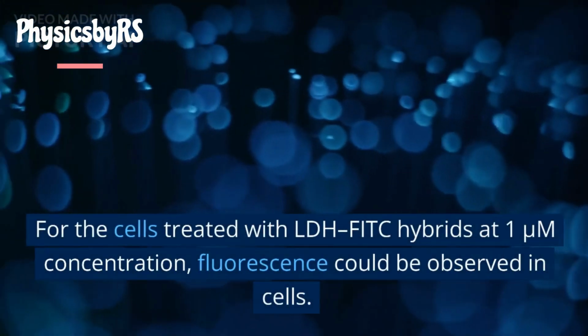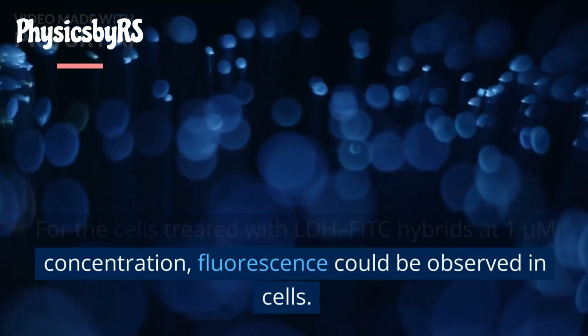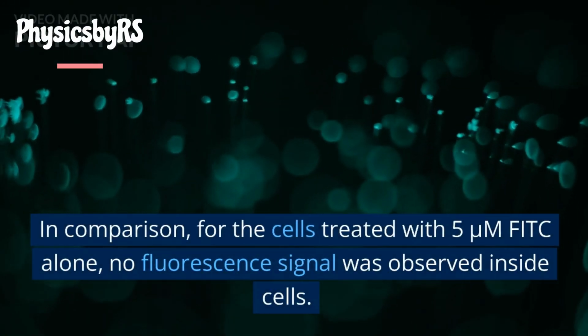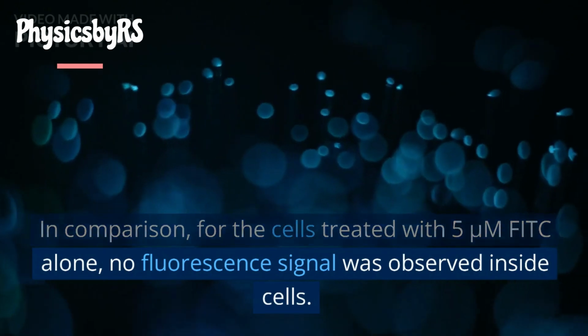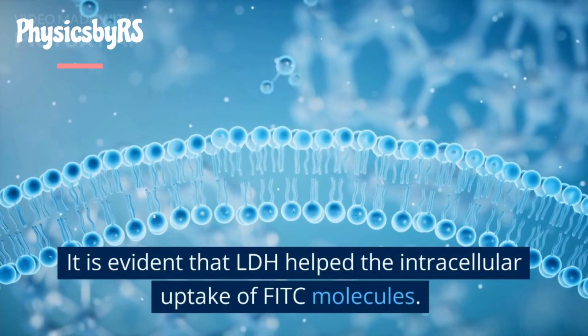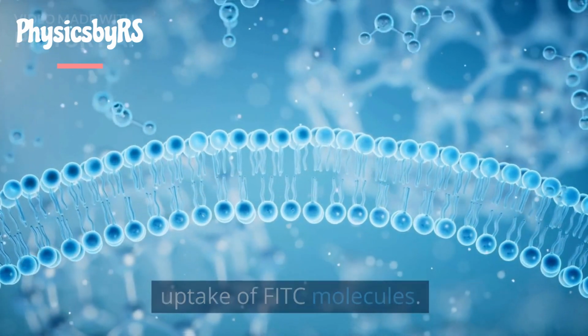For the cells treated with LDH-FITC hybrids at 1 μM concentration, fluorescence could be observed in cells. In comparison, for the cells treated with 5 μM FITC alone, no fluorescence signal was observed inside cells. It is evident that LDH helped the intracellular uptake of FITC molecules.